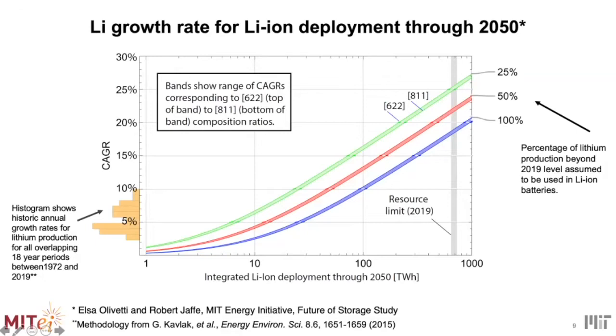But the bigger problem is that it depends on where this lithium goes, so here we have 100%, 50%, 25%. And what that means is that the additional mining of lithium, 100% of it goes towards, in this case, lithium ion batteries versus 50 or 25% of it. And then over on the left-hand side, we have an axis which is compound annual growth rate of production, which means of mining, right? And so if by 2050 we reach 100 terawatt hours, and we use all of that lithium for lithium ion batteries, we need to increase production at a rate of 10% per year now through 2050. And if you look at the historical scaling of production, which is these yellow bars over here, what you find is that it's at the upper limit, right? And so the basic message here is that it's a very heavy lift to get there, right? Not theoretically impossible, but a very heavy lift.